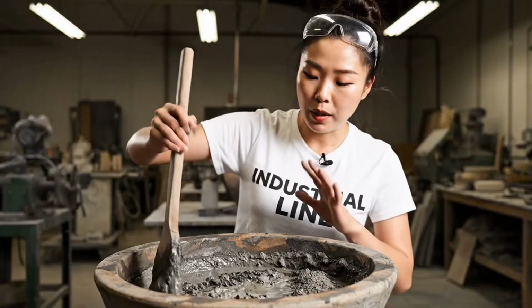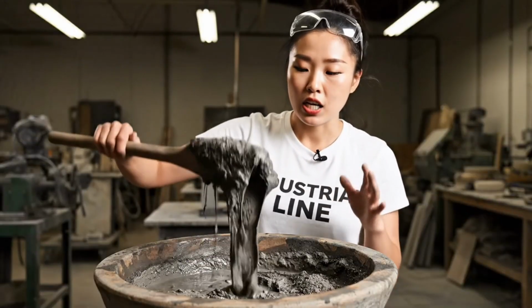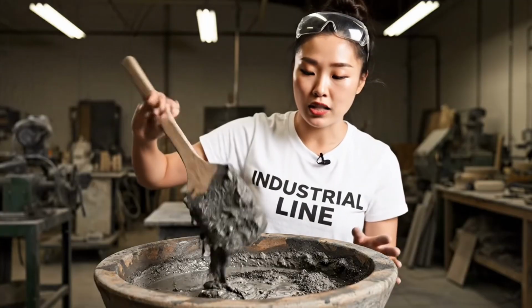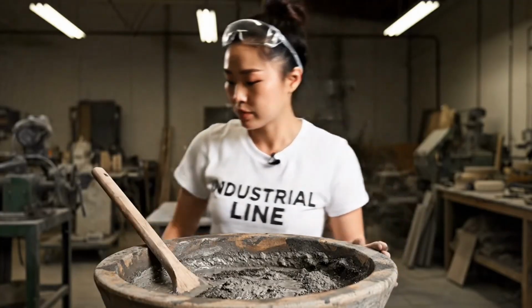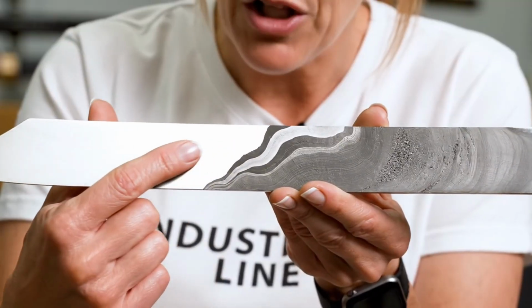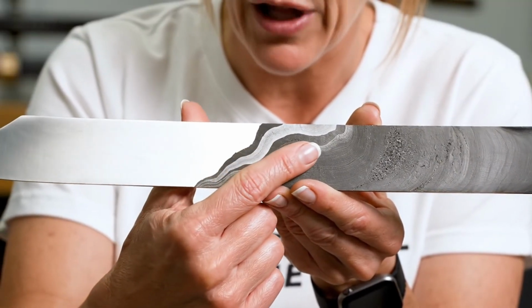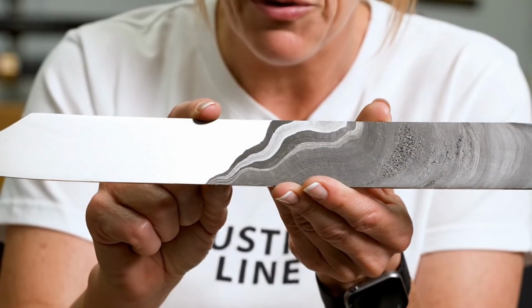This clay coating will be applied to the spine of the blade. During quenching, it insulates the spine so only the edge hardens. As you can see, the hamon clearly separates the hard martensite edge from the softer pearlite core. This is where the phase transformation occurs.